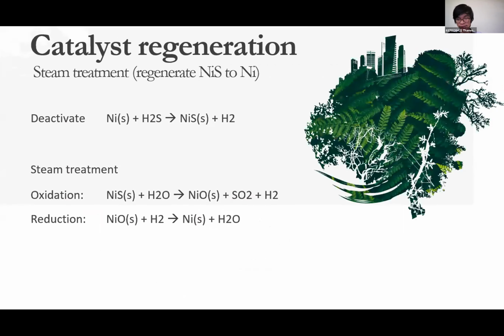The third method is steam treatment. The sulfur poison of nickel is regenerated by steam air and steam hydrogen treatment. We attempted to regenerate it by treating it with steam. The steam treatment leads to the oxidation of nickel sulfide to nickel oxide, and the catalyst is then reduced from nickel oxide to the active nickel site under hydrogen conditions.